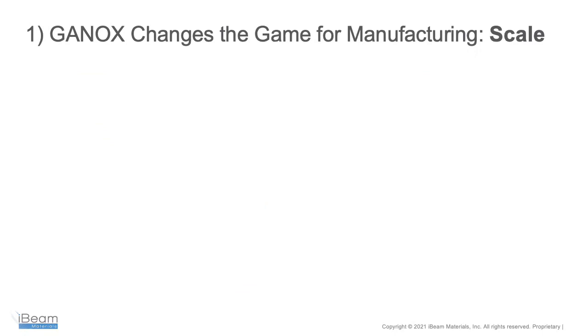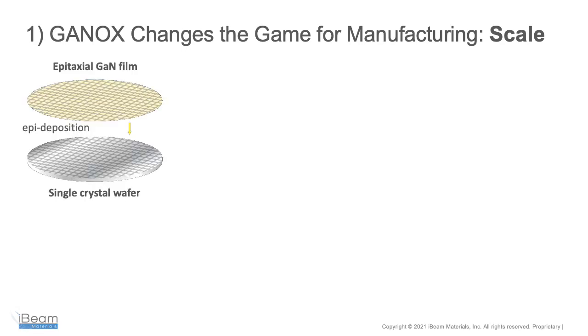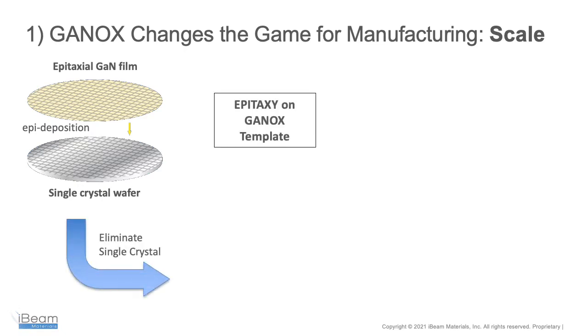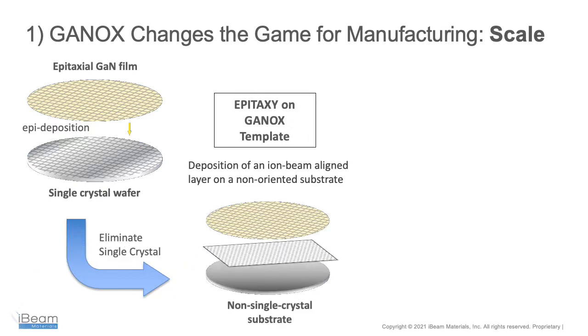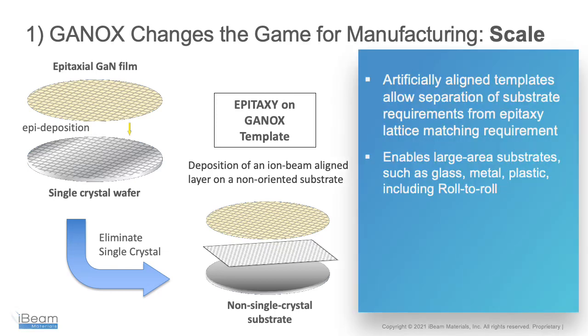As I said before, the Ganox platform first transforms how GaN LEDs can be manufactured. And this primarily means scale. Standard epitaxial deposition relies on single crystal wafers. These are typically scaled up by going from 2-inch wafers to 4-inch, 6-inch, 8-inch, and so on. By using the Ganox process, however, non-single crystal substrates can be utilized, and these allow one to go to much larger areas. All we need to do is to pre-deposit an ion beam aligned layer on top of this non-single crystal substrate to transform it to a template for epitaxy.